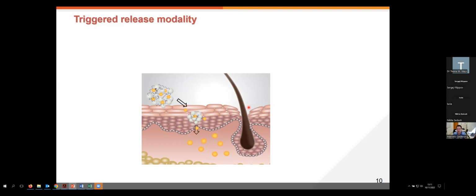interesting for drug delivery applications, because on the skin we actually have a natural thermal gradient. On the surface of the skin, the temperature is around 32 degrees. And when we go inside the first layer of the skin, this temperature increases by several degrees until we reach 37. So we have here a really nice window of temperature changes that could be used to trigger changes in our thermoresponsive polymers. And this is why we were interested in using these thermoresponsive materials in this application.